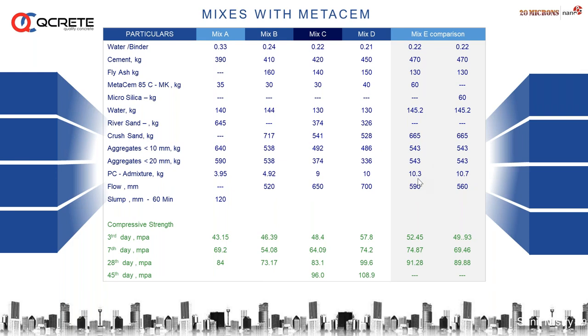less compared to the other mineral admixture mixtures, comparable, and the flow part is also accepted, as well as the strength part. On the third day it is more than 50, it is possible, whereas at 28 days 91 plus compressive strength is achievable against 89.86 of the analog product actually. So this is the difference, and not only this mix design, we did a lot of trials.